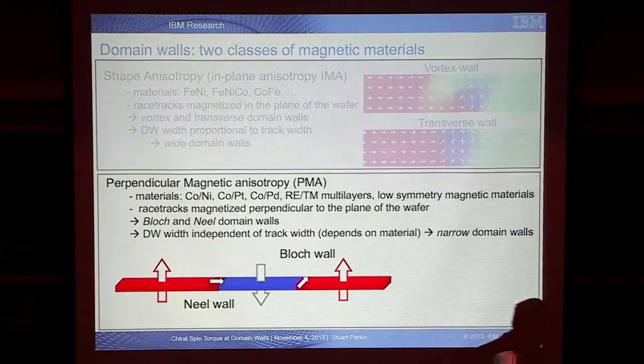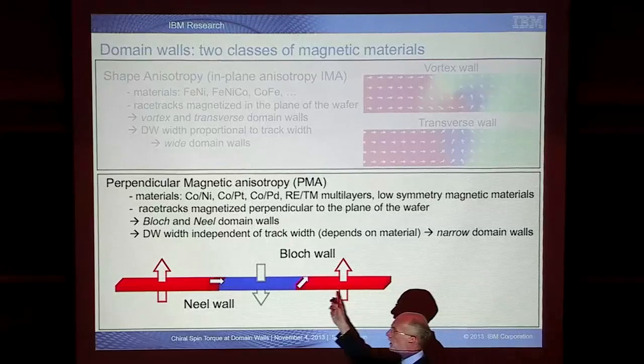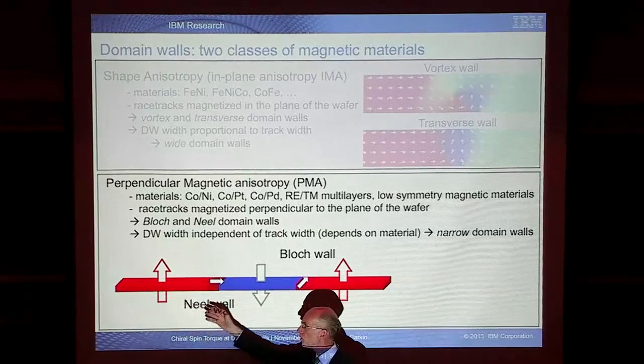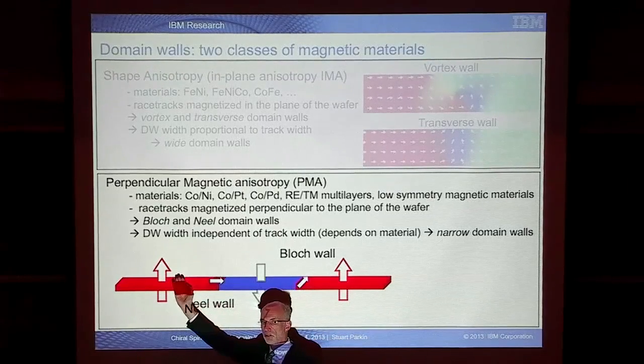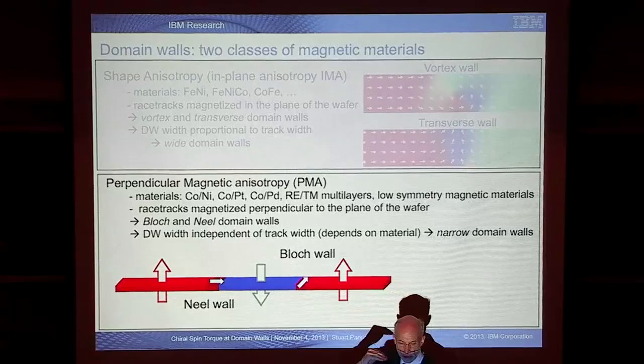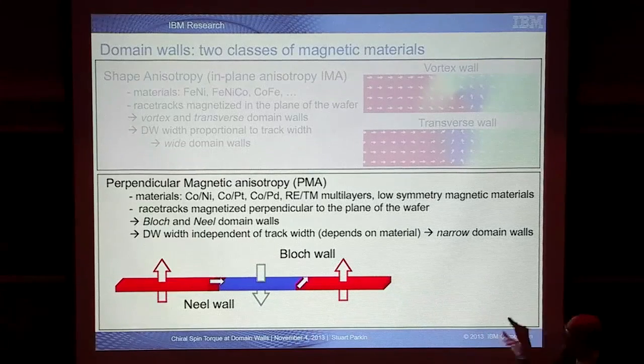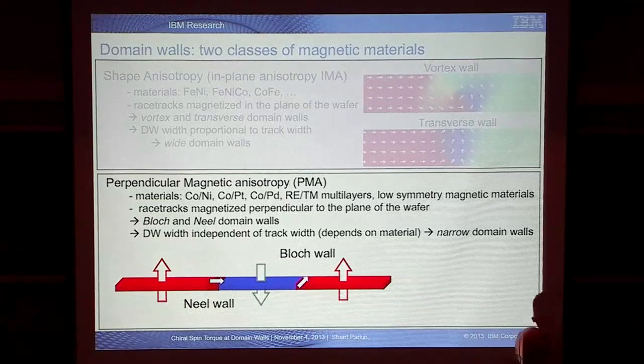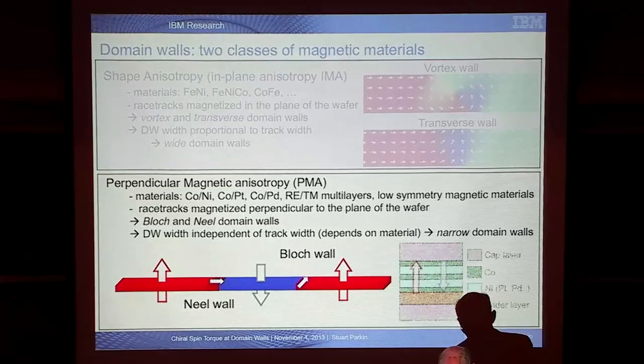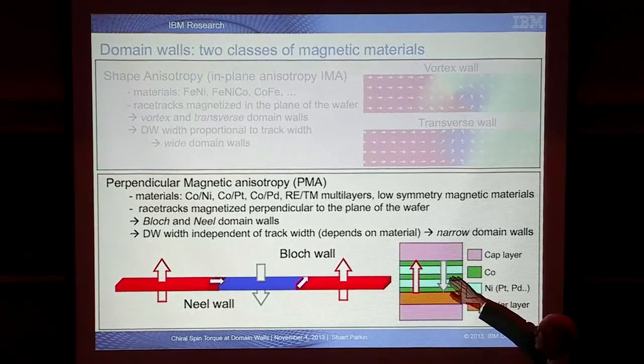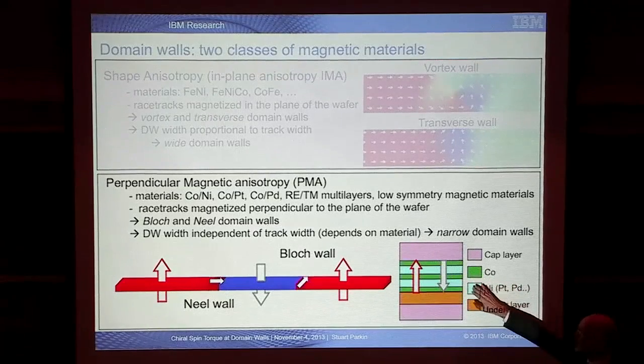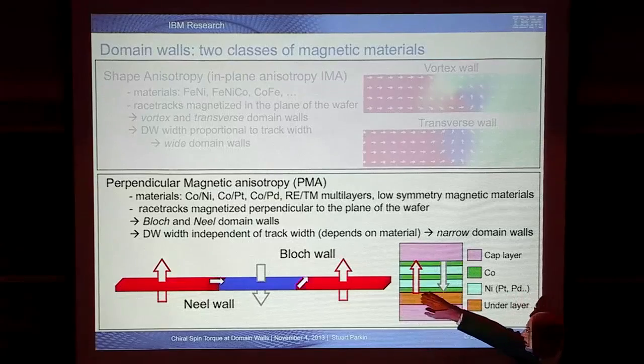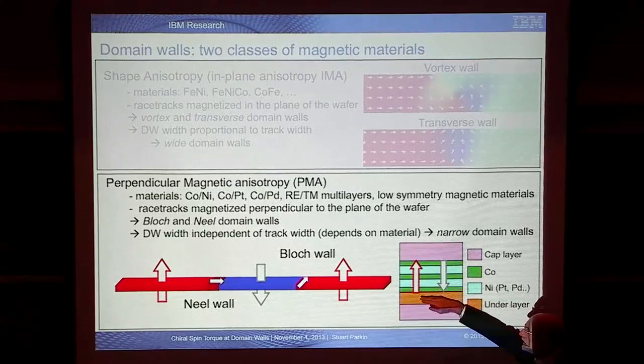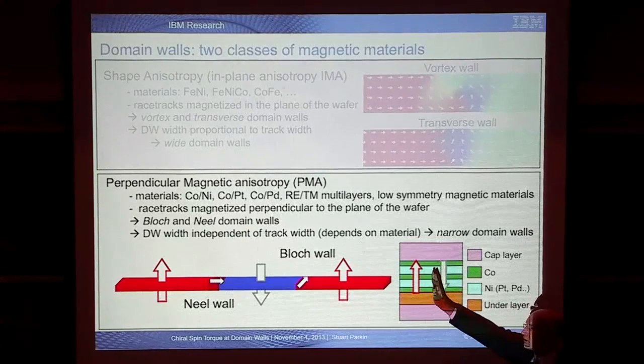All I wanted to comment on here was that to build dense racetrack, we have to use materials where the racetrack wires have their magnetic moments oriented perpendicular to the racetrack. And we can do this again by using atomically layered materials in which, on the atomic scale, it turns out that the interfaces, for example, between atomically thin cobalt, about 1 atomic layer thick, and 3 atomic layers of nickel, then the magnetic moments want to be perpendicular.